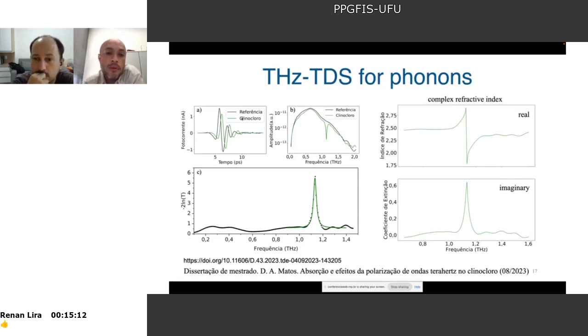In this case, I'm showing this mineral clinochlore. So it's like a small rock. It's a van der Waals mineral that we started to study recently. And the reference here, since there is no substrate, it's a natural mineral, then we only measure the air, right? And the blue one is the light transmitted through the sample, this clinochlore, right? You can see that there is a shift in the phase. This is because the sample, of course, has a different refractive index. And also there is some modification in the time domain. What we do now is to apply a Fourier transform.